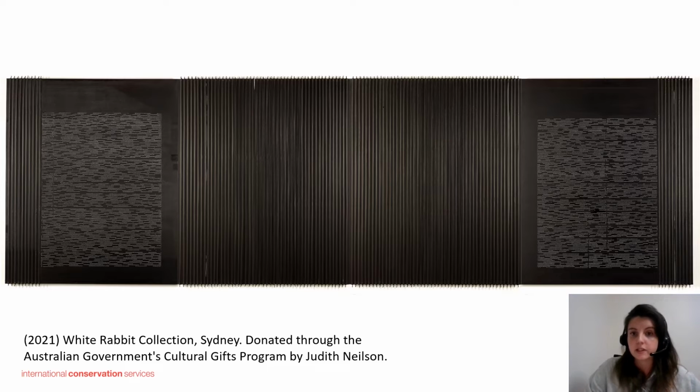Most preventative measures in conservation focus on maintaining the environmental conditions for the paintings. However, the usual standard and strict 20 degrees and 50% relative humidity cannot always apply due to the glass transition temperature of acrylic paints. Acrylic paints are understood to have a glass transition temperature close to room temperature. At lower temperatures, the paint could crack, while at higher temperatures, the paint could become sticky, leading to the danger of the surface dirt becoming entrenched into the paint itself.